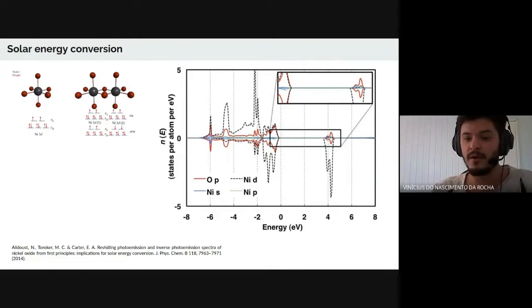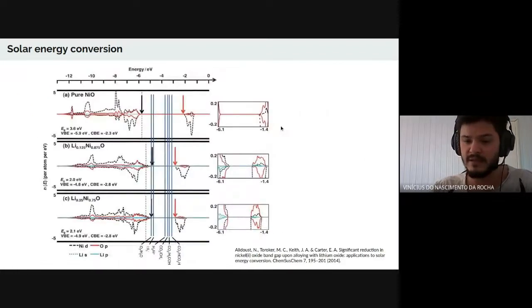Quantum simulations can explore the doping and alloying of such materials to optimize key properties such as band gaps, band edge positions, charge carriers, and ion mobilities. For example, nickel oxide has a large band gap that results in only meager light absorption. DFT calculations indicate that alloying nickel oxide with lithium oxide will lower the band gap by as much as 1 electron volt without affecting other favorable properties.